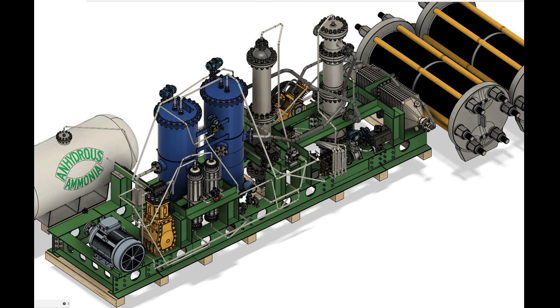For small-scale reciprocating compressors, the efficiency is surprisingly close to the benchmark centrifugal machines, with the best-in-class reciprocating compressors drawing around 0.20 kWh per kilogram of N2. For hydrogen compression, a realistic figure is around 3.5 to 4 kWh of power per kilogram of hydrogen at 300 bar, using intercooled reciprocating piston compressors, translating to just under 600 kWh per ton of ammonia.